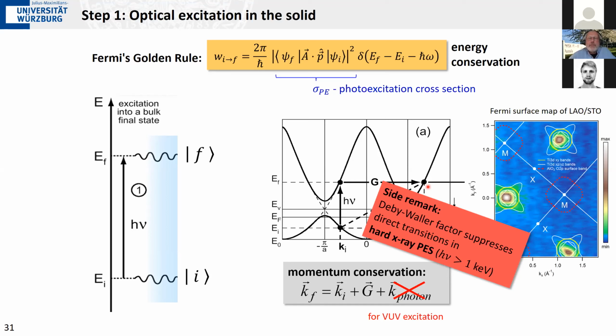And a similar thing happens also in photoemission. If the temperature is not low enough, you may smear out all of your momentum information. And this is why very often when you go to X-ray photoemission, nobody talks about momentum conservation anymore. It's always restricted to low photon energies, because there the Debye-Waller factor, which scales basically with the photon momentum, is not as important.